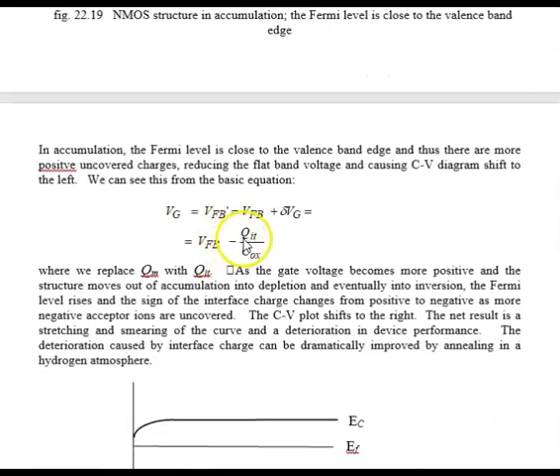And that is what is shown here, except I replace the Q sub m by a QIT. So we have a negative shift in the flat band. Flat band moves to the left, and that's kind of important. Well, we're generally not interested in accumulation. That's kind of a boring structure. But really, we want to go into depletion and inversion.